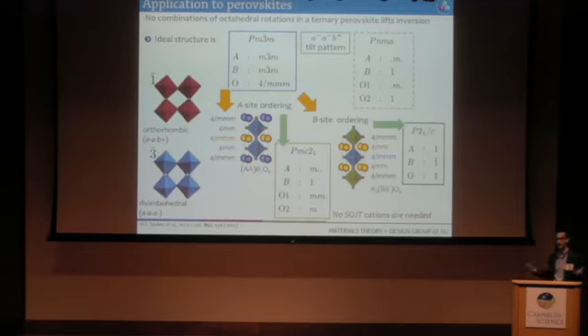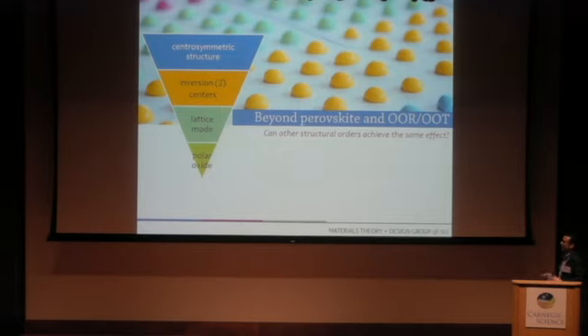This is nothing about the chemistry. This is purely a crystallography argument. The question is, then, can this phase be made, synthesized? Is it stable? Is it metastable with respect to, say, the unordered phase? And that's a question we can address using computational methods, or if you have a super enthusiastic collaborator who will try to make a lot of materials. Okay, so that's the concept. What I want to do is extend this then beyond perovskites and octahedral rotations and tilts. Can we use other structural orders to achieve the same effect?